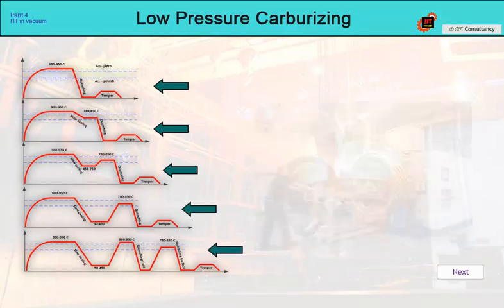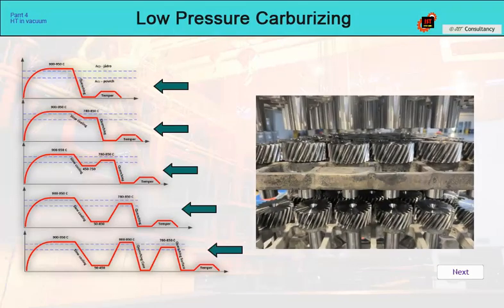However, if it is necessary to quench from the optimal quenching temperature, then we must let the furnace cool down spontaneously to the required temperature, heat the load again at this lower temperature, and then quench. It will cost us 2 hours of non-productive time. Other hardening methods, with a decrease below A1 or below MS temperature, are so unfavorable that these processes cannot be carried out responsibly for economic reasons.